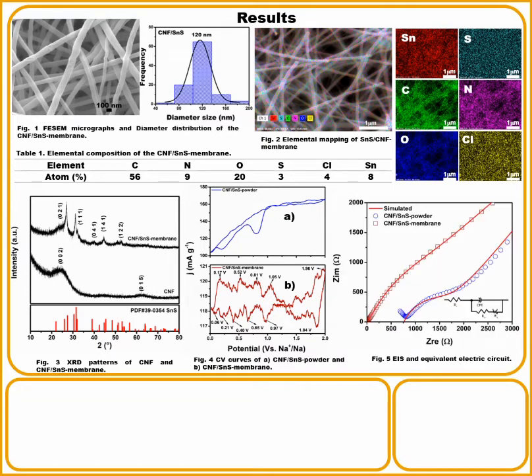On the other hand, the electrochemical impedance shows that the carbon nanofiber membrane with tin sulfide electrode has a lower resistance compared to the pulverized one, which improves the transfer of electrons in batteries.